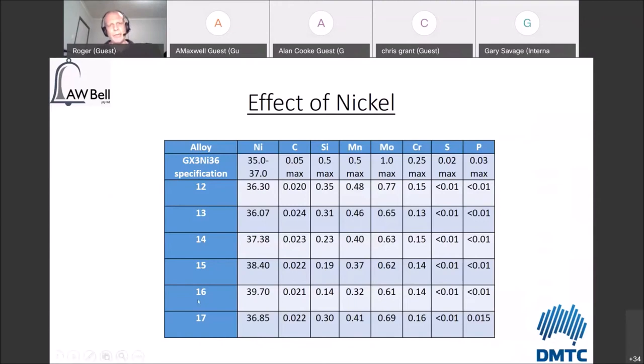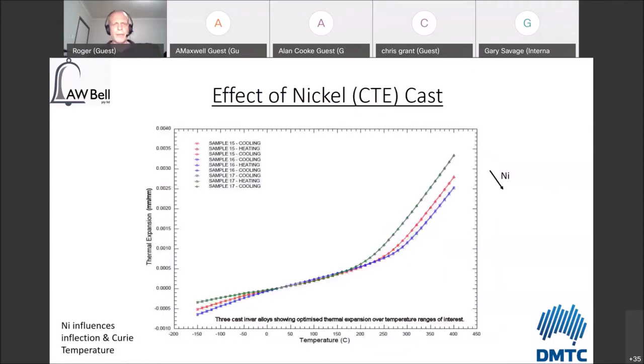So we have here alloy 16 with around 40% nickel, maintaining around 36% in a few of these materials, and around 37 to 38% in some of them as well. Carbon was kept around 0.02 as well as we could. Silicon, keep it pretty low. Manganese, keep it below a sensible level. And the moly's still in there, and a little bit of chrome, as mentioned earlier. Sulfur and phosphorus are both very, very low. These are the different trials that ran through to look at the effect of nickel, and this summarizes the result very nicely.